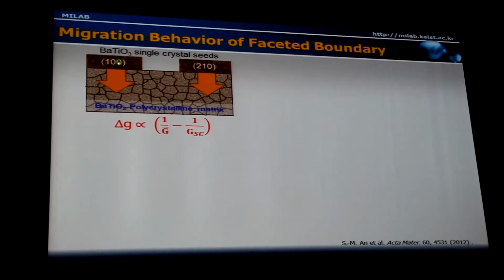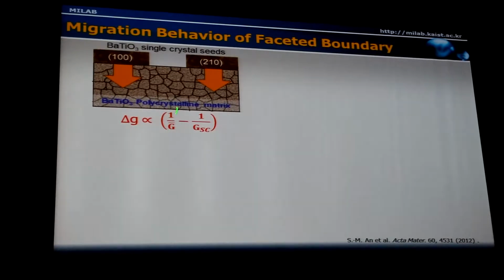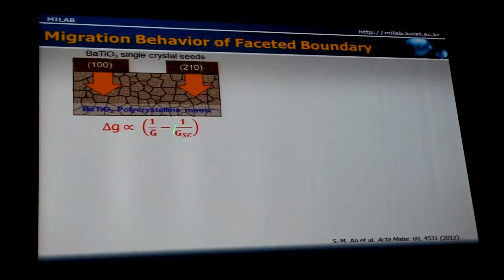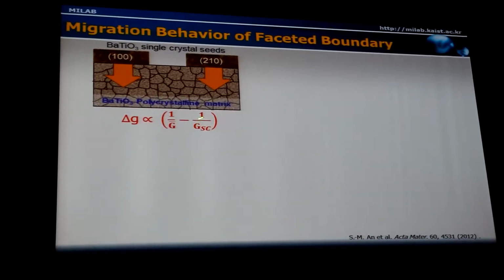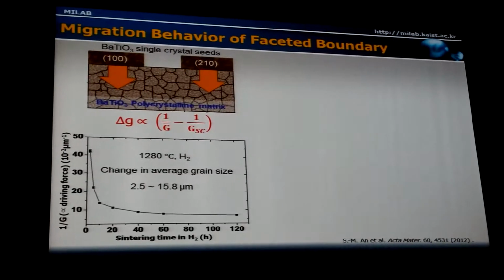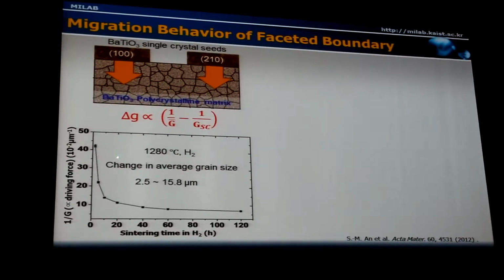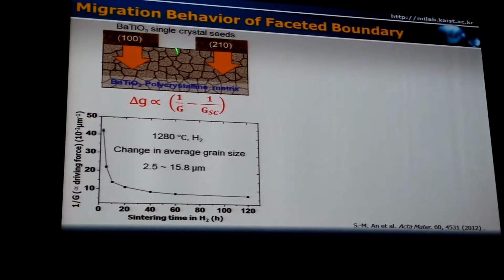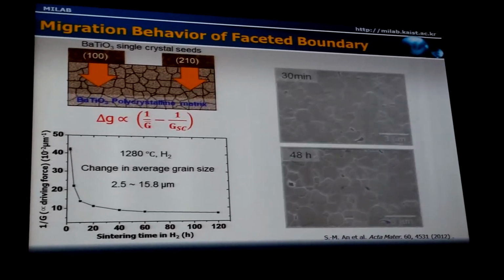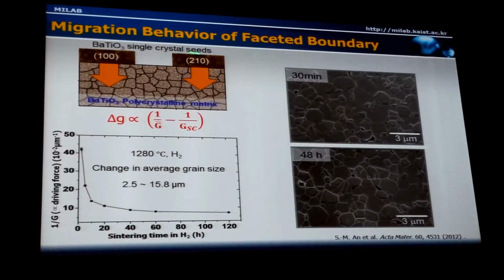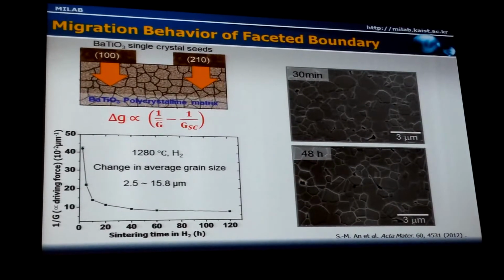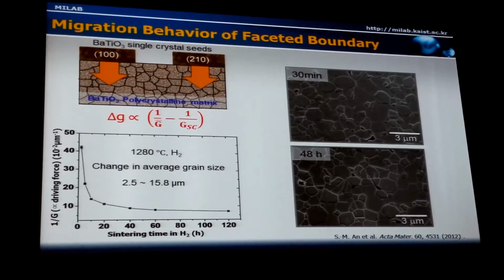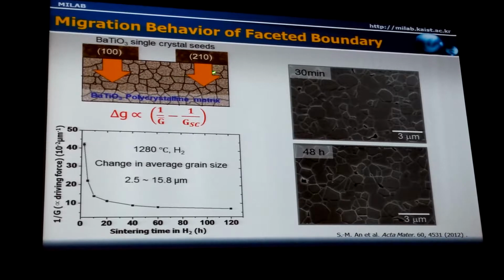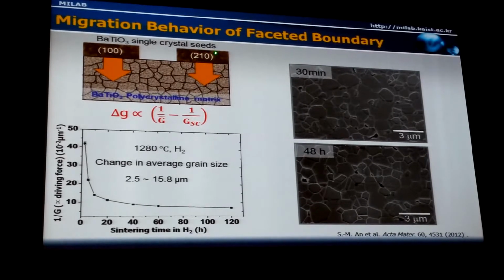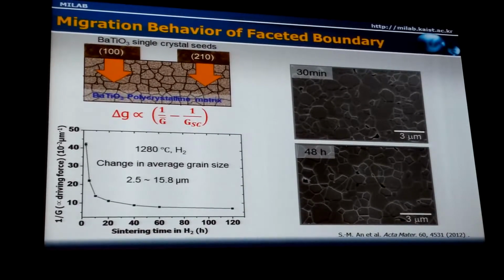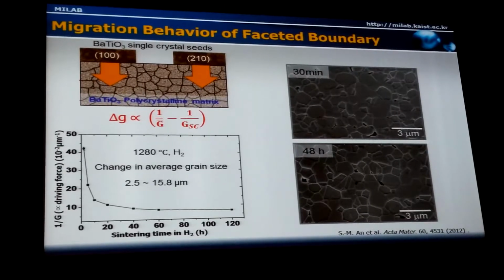Of course, the driving force for the migration or growth of the single crystal is expressed by the difference between the inverse of the average grain size in the polycrystal and the inverse of the average grain size of the single crystal. This is about 0. Then we change the average grain size of the polycrystals, and that means we change the driving force for the growth of the single crystal. During the annealing, during the growth of the single crystal, there is essentially no change in microstructure in the polycrystal. That means we were able to keep the driving force constant. So we just measure the growth distance, then we can estimate the kinetics of the growth of the single crystal. That means the migration of the faceted boundary.